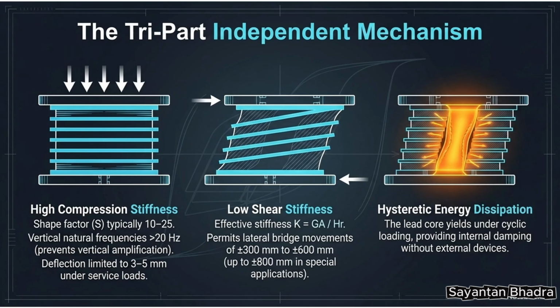Second, low shear stiffness, defined by effective horizontal stiffness K equals GA over HR, permits large relative horizontal bridge displacement ranging from plus or minus 300 millimeters to plus or minus 600 millimeters, and up to plus or minus 800 millimeters in extreme cases. Third, hysteretic energy dissipation occurs internally via cyclic shear yielding of the central lead core, eliminating the need for external damper assemblies.